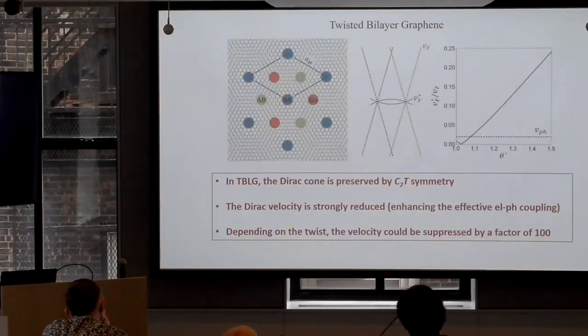So now we need to take that graphene and convert it into twisted bilayer graphene. So twisted bilayer graphene, this is the picture. And basically we use the same band structure everybody uses. This is the MacDonald band structure. And this is a calculation of the graphene Fermi velocity as a function of the twist angle. This is the famous magic angle where, in this zeroth order theory, the velocity goes to zero, okay? Now, this is the Fermi velocity of graphene. This is the phonon velocity of graphene.